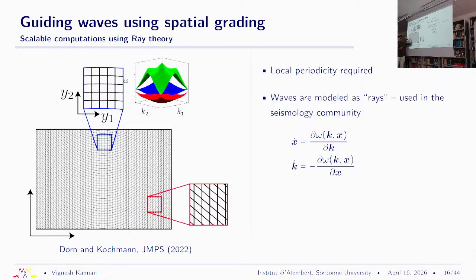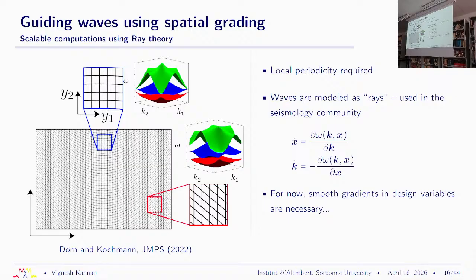where if I assume local periodicity, right, this is purely in a computational sense, if I can assume local periodicity of my unit cell architecture, and if I know the dispersion of that locally periodic architecture, I can create gradients of this periodicity and model the propagation of rays using the time derivative of the position and time derivative of my k vector, right? And this is something that comes from seismology, and Charlie has done significant work in this direction in the last few years. But this also means that you need very smooth gradients if we actually want to realize these devices experimentally or even in actual device design.